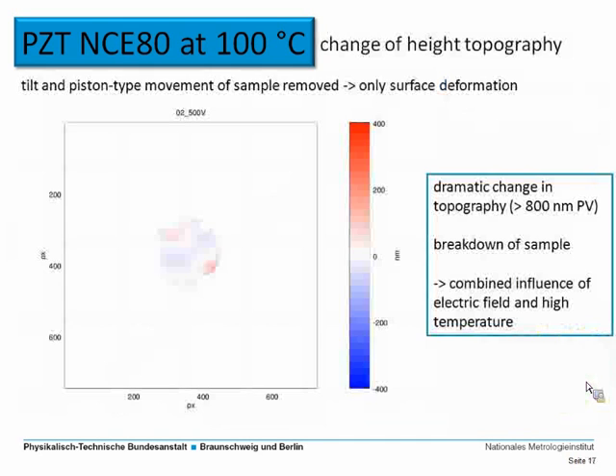So this in turn makes the change of height topography much more interesting than in the case before. Again, piston type movement and tilt are removed, so it's only the surface deformation, but notice the scale. This is almost 1 micron in surface deformation change now, and you can see it also in the movie I'm going to show in a moment, that the surface shape at the beginning and in the end of the movie look quite different, so there is really some big change induced, and this is due to the breakdown of the sample.